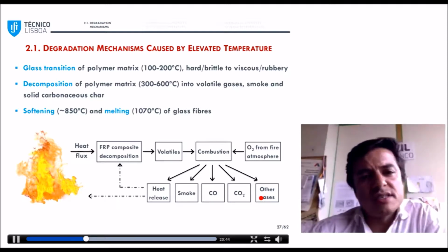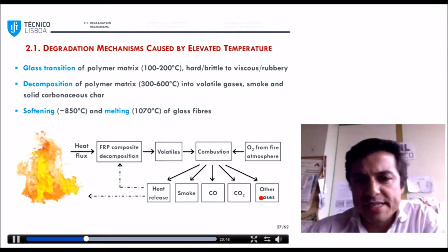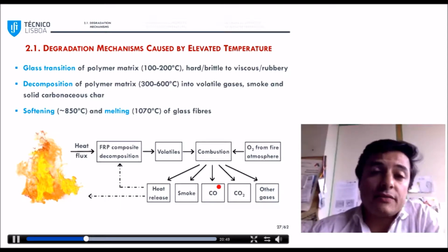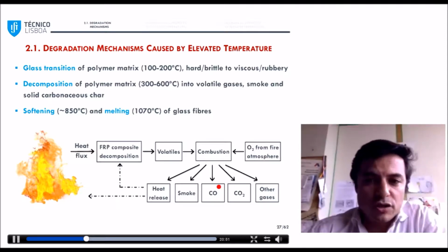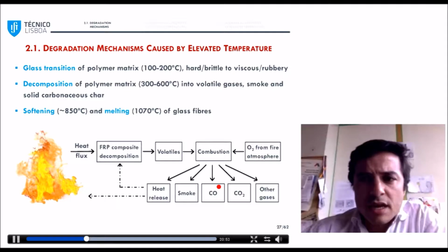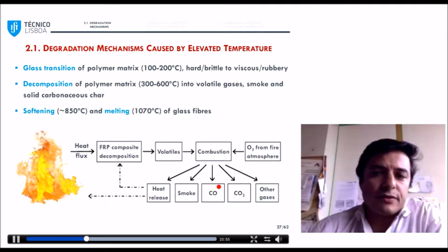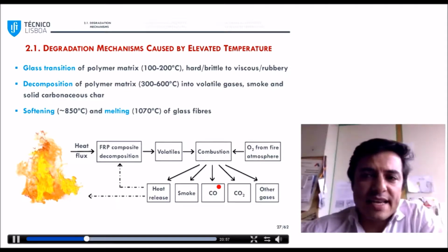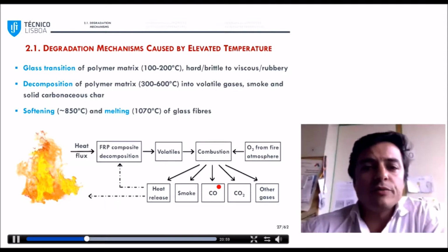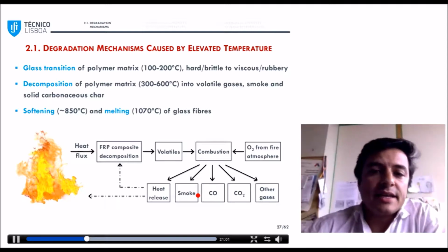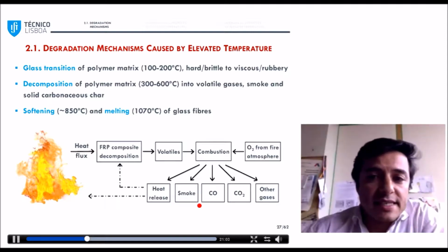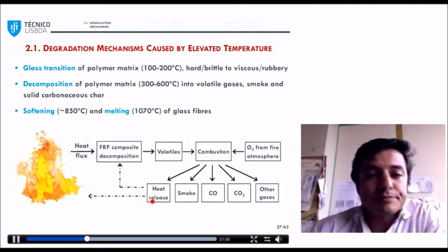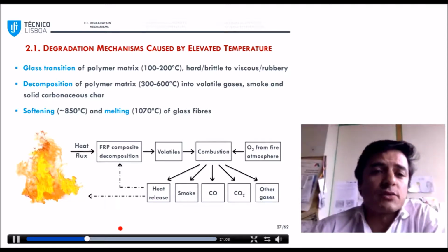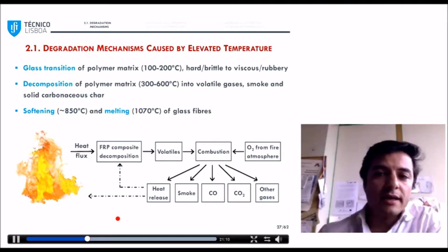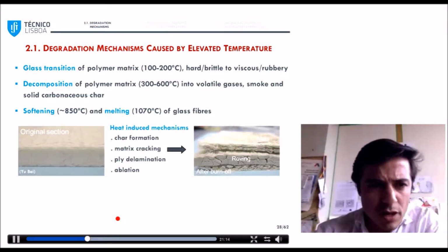So the second mechanism occurs for higher temperatures, somewhere between 300 and 600 degrees. And for that, we have the decomposition of the polymer matrix. So in the presence of oxygen, the volatile gases that are formed ignite and result in toxic gases, smoke, and heat. And finally, for temperatures around 1000 degrees, the glass fibers soften and melt.